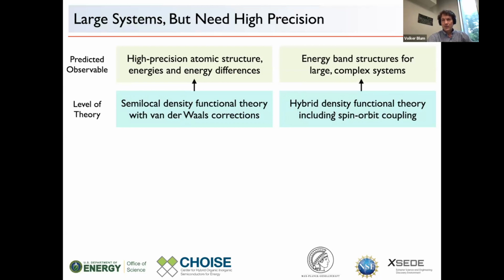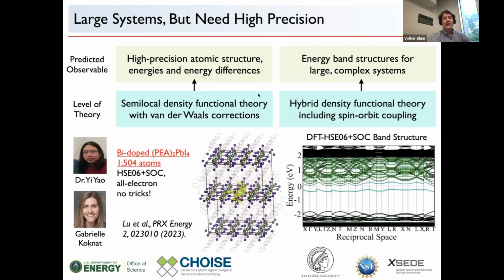Critically, we need to include relativistic effects, so spin-orbit coupling, and we do. I won't go much into detail about the validation, but we validated this indirectly using optical experimental data many times, and it seems that especially energy level band alignments between the materials seem to come out very reliably. But we can do this.